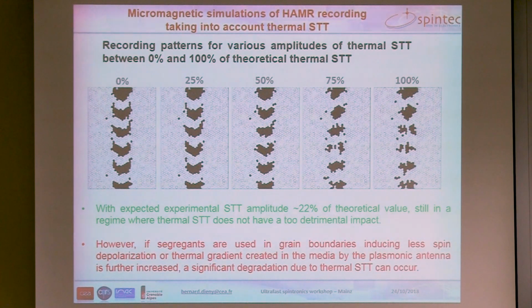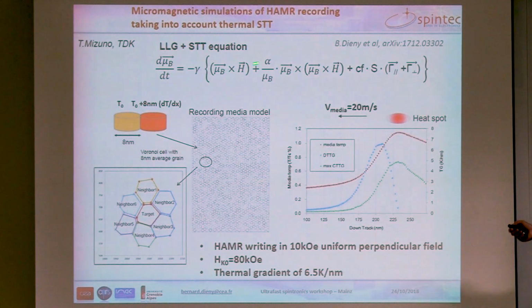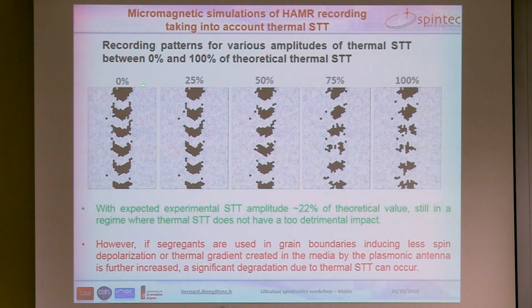and a thermal gradient of 6.5 Kelvin per nanometer. And here what we did was to vary the amplitude of the spin transfer torque, which was plugged in the LLG equation. You see here the usual terms, and here the two terms due to the thermal spin transfer torque, with the prefactor being the amplitude that we calculated previously. But this amplitude we multiply by this factor, and with the parameters that we determined, we are at about 22% of the amplitude calculated from our initial model. So we are somewhere around here.